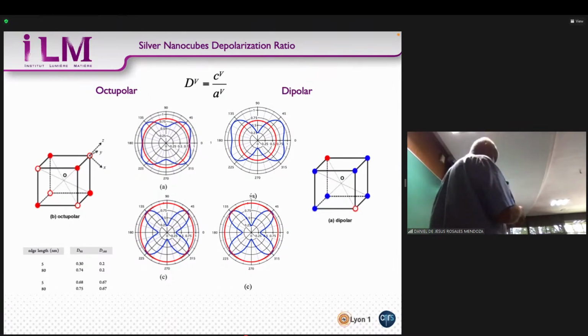Therefore, we can really say that the response is closer to something like this than like this. There's no chance that all the corners will be exactly, perfectly the same. So it's more probable to have a distribution of 8 slightly different dipole corners than perfectly identical ones. Therefore, you will be closer to this picture, and this is indeed what we see. So this coefficient gives information on the nature of the response, whereas the previous one was giving information on the weight of retardation.